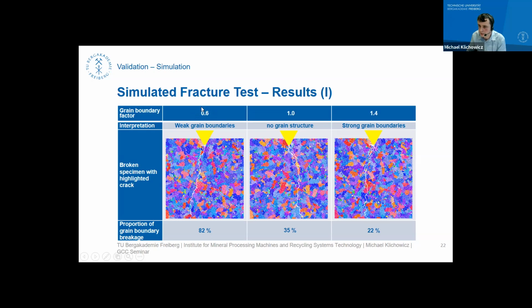If we have a lower factor, a weak grain boundary factor, that means that our grain boundaries are much weaker than the bondings in the grain. And if we have a high grain boundary factor, our bondings between the grains are much stronger than the bondings inside the grains. And here is the proportion of grain boundary breakage of a real experiment, and that is about 55% of the breakage went along grain boundaries. And we can now compare this to the proportion of the grain boundary breakage in the simulation. And we are somewhere in between factor 1 and 0.6.